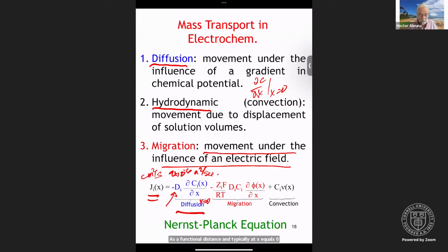So this is the contribution of mass transport due to diffusion. Migration, again, you have the diffusion coefficient, the concentration of the ionic species. Z is the charge, F is Faraday's constant, then the gas constant and temperature. And then basically the electric field at the interface. Partial phi, partial X, what's the electric field gradient coming from the interface? And then convection, again, concentration, and it's basically the linear velocity.